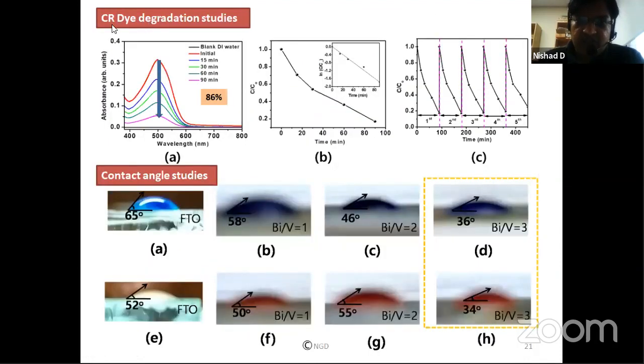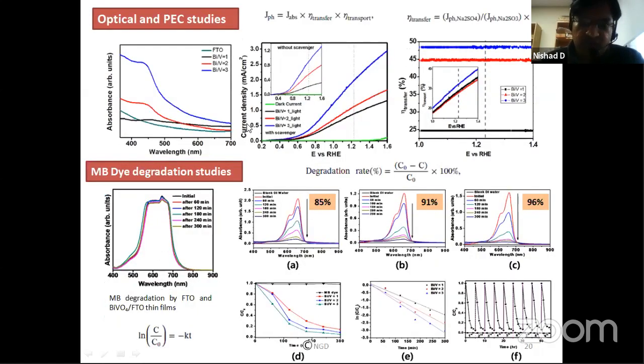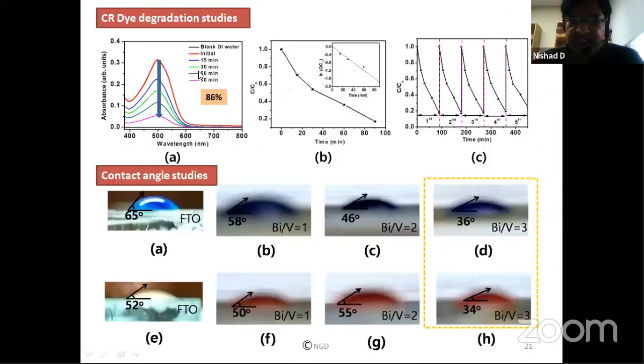We also tried to see in putting in Congo red dye. So earlier we tried for a methylene blue dye here, and now we tried for a Congo red dye. So what you can see is that now this is a faster reaction, and within 90 minutes you can achieve 86% of your dye degradation. So this means this facet is more active towards the Congo red dye.